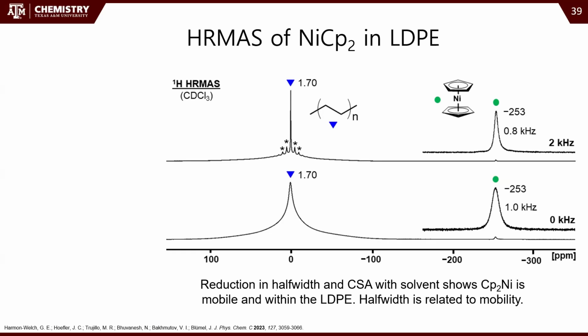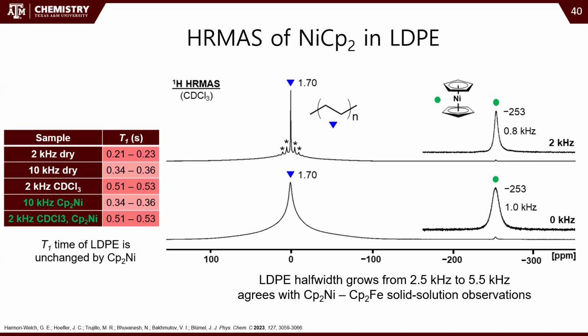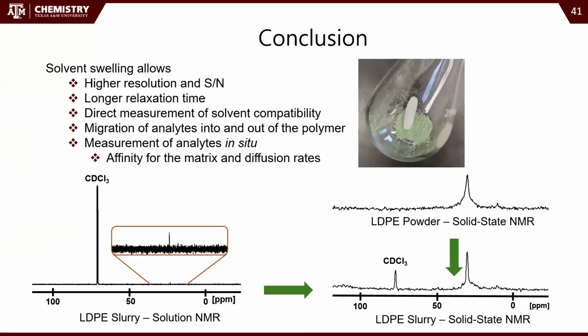Also, we see the LDPE signal has an increased half width over just regular HRMAS. So T1 times don't observably change for the LDPE, but the half width grows from 2.5 kilohertz to 5.5 kilohertz. And that's kind of in line with the literature that we've seen previously, or that my coworker Gabby measured actually, that nickelocene and ferrocene solid solutions will have, the ferrocene will have the same T1 time, but it will have a broader half width. So that's kind of interesting, but I guess not too unexpected.